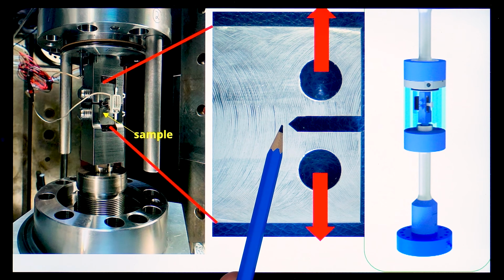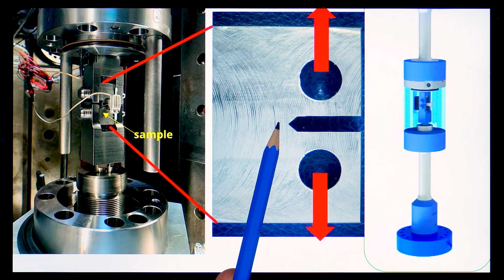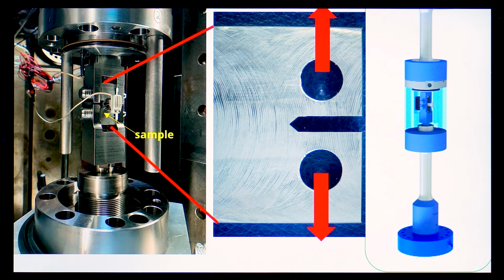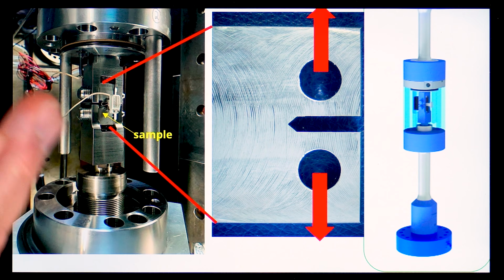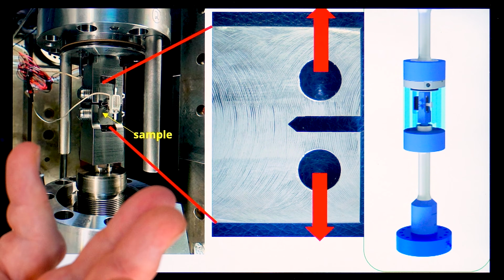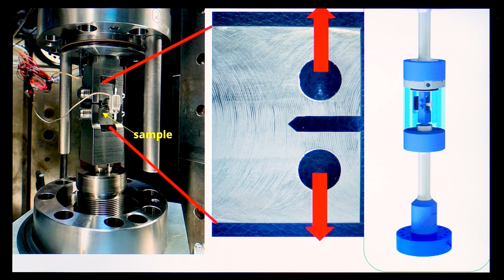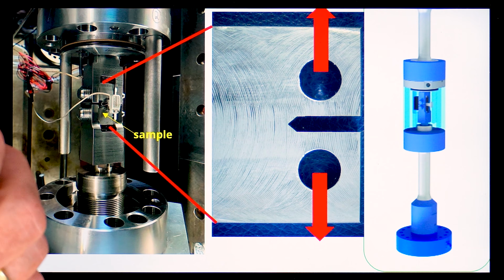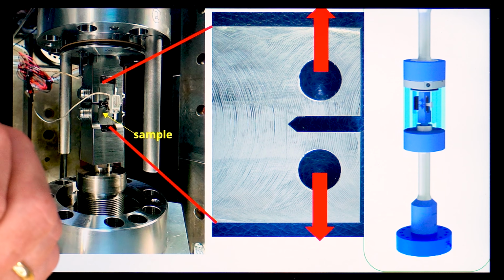If the crack has started and has a specific length, then we put the sample into a chamber, which is also completely under hydrogen. Then we do the test. Inside the chamber we also have a fatigue force, and we will see how the crack runs under hydrogen conditions, in a hydrogen atmosphere.